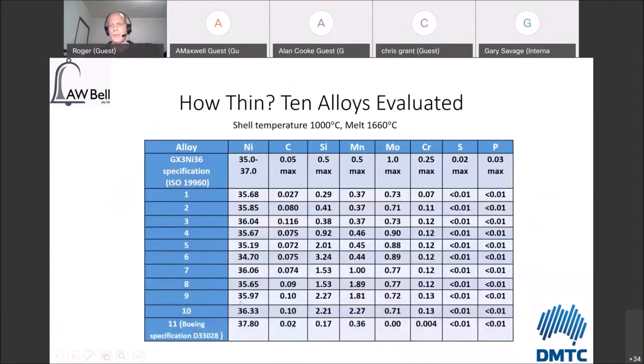So the 10 alloys that were evaluated in the first round of testing, you can see here, we maintained between close to 35% up to around 36% nickel. Now these were all air melted, I would say, as well. The pour temperature was 1660. The shell temperature was 1,000, as already mentioned. And what you can see here is the variations that we made. We had varying carbon contents, silicon contents, manganese contents. We mostly tried to keep the molybdenum and chromium fairly standard.